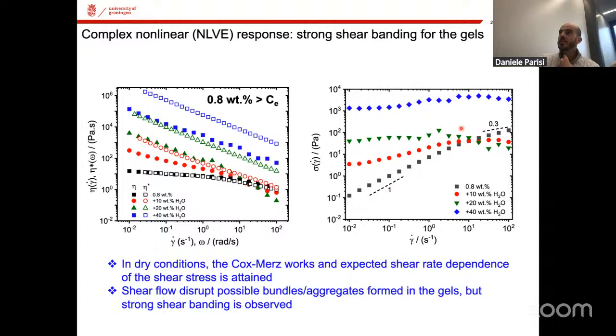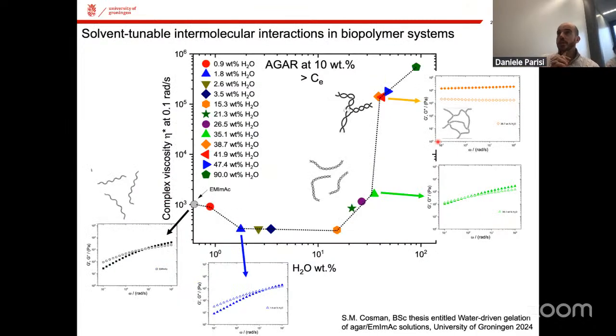So since the stress is basically the product between the shear rate and the viscosity, this product is basically constant. Okay, and this has been seen actually with colloidal gels exhibiting, let's say, strong shear thinning. So this brings me to the second and last topic.